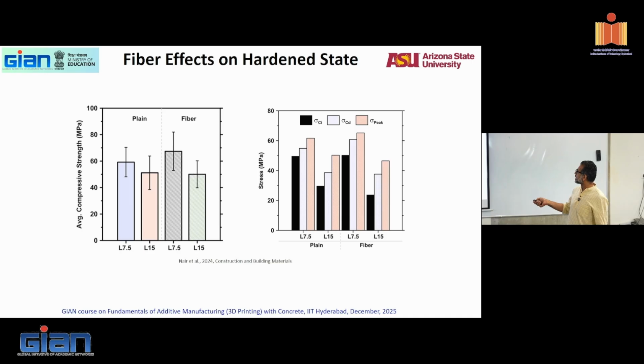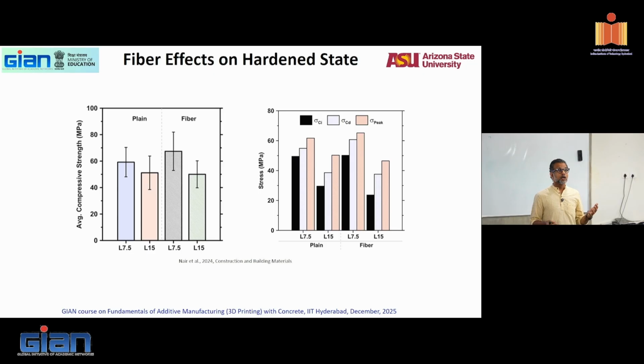Plain versus fiber reinforced. Compression, really fibers don't do much in compression at really small volumes. At very high volumes, when we use UHPCs, ultra high performance concretes, where up to 3% by volume of fibers are used, then you will start to see an increase in strength. This is about 0.3%. You will see almost no effect in compression, but you will see effects in tension and flexure.